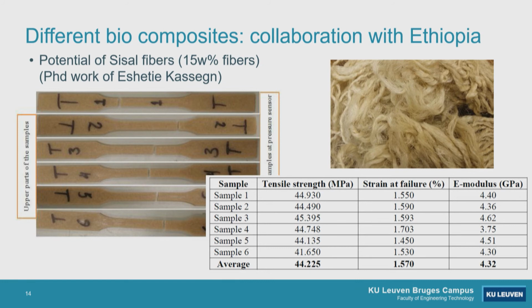If we look at properties, we end up with an average tensile strength of 44 megapascals, really brittle behavior, only 1.6% of elongation is possible, and an E modulus of 4.3 gigapascal, so only a slight improvement compared to the neat PLA. Of course, also the idea was there to use a plasticizer to avoid the too brittle behavior of these materials.